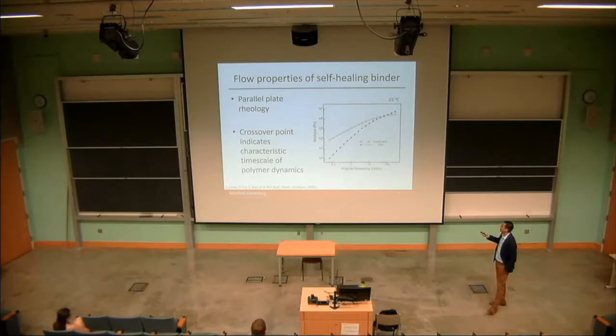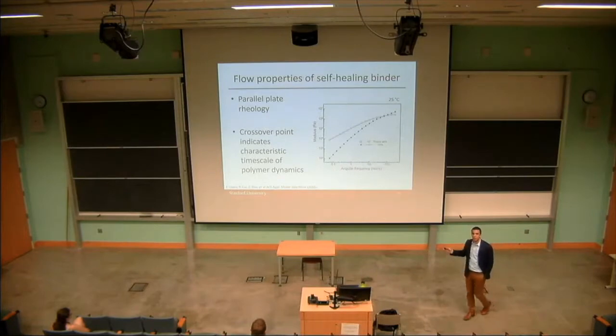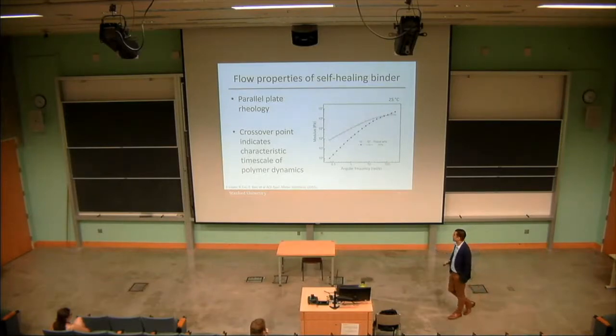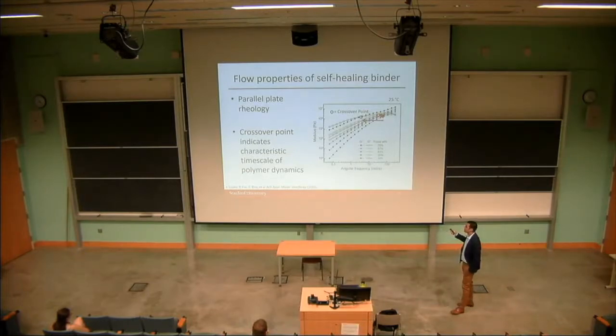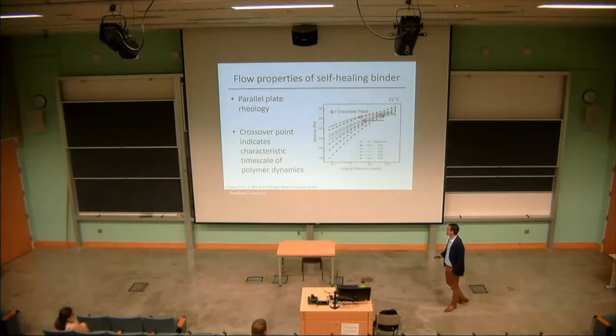And then as we go faster and faster, we reach a crossover point, and then finally it starts to behave like a solid. So at low frequencies or long times, this material is flowing, but when we probe it very quickly, it begins to behave like a solid and respond solidly. So we can do that for all of these, and what we see is the crossover point, which is really that characteristic time scale of the material. So when you're probing at that time scale, you have a match between liquid-like and solid-like properties, is moving to longer and longer time scales. So we're getting more and more solid-like materials as we increase the cross-linking.